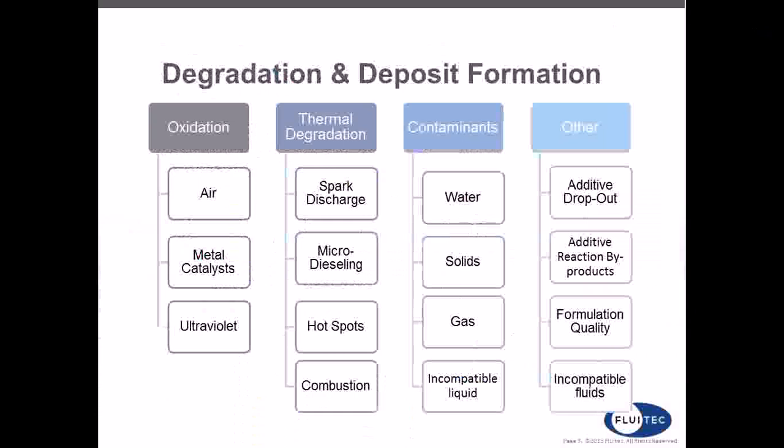So there could be a wide range of different mechanisms that can be beating up oils. And often people assume that oils are aging and varnishes are being formed due to oxidation. And oxidation certainly is one of the key modes of fluid degradation. Oxidation is a fairly slow reaction, and essentially is a reaction of any substance with oxygen. And then there are several things that could speed up the rate of oxidation.